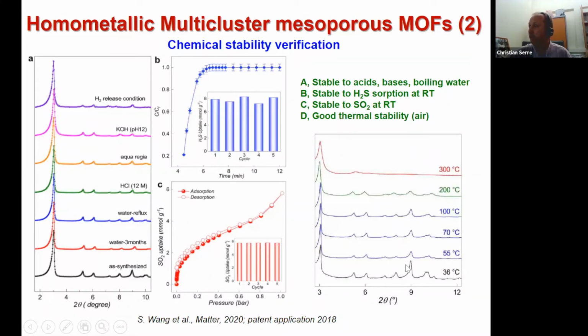And here, this is a variable temperature PXRD, and you can see that up to 300 degrees C, we can keep the structural integrity of the material. At 300, we see the beginning of peak broadening, but this is also known in Zr6-based MOFs, where you have some dehydroxylation at such temperatures. And based on TGA, we are really convinced that it is more a loss of long-range order rather than a real degradation of the structure.